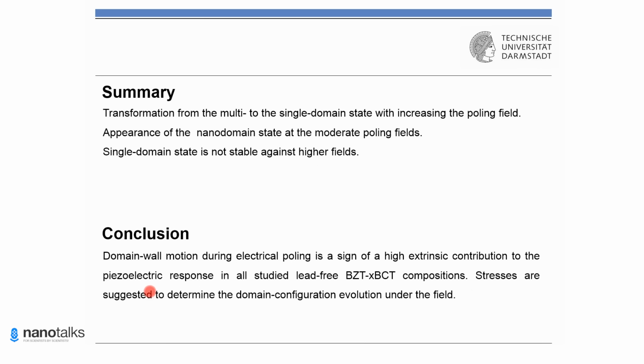Okay, so finally I just would like to summarize what I was talking about today. First of all, we observe the transformation from a multi to single domain state with increasing the poling field. We saw the appearance of nanodomain state at the moderate poling fields. We saw that this single domain state is not stable against higher fields and transforms again to our multiple domain state. So just in conclusion, what can we tell? Basically, domain wall motion during electrical poling can be a sign of high extrinsic contribution to the piezoelectric properties in our material. And stress is suggested to determine the domain configuration evolution under the field.